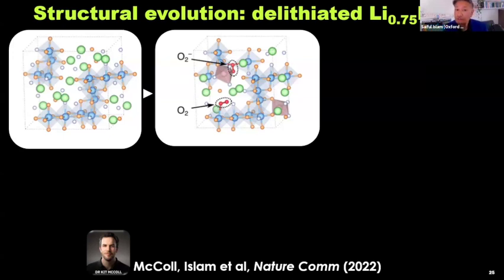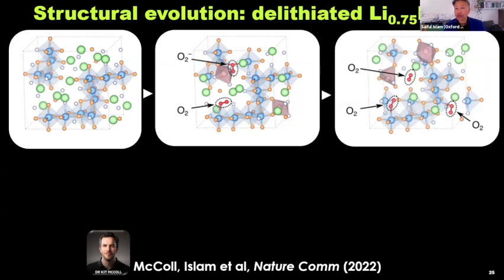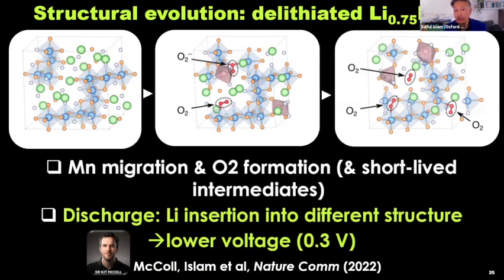And that's interesting, because these superoxide and peroxide species could be transient, because the thermodynamic product is again molecular O2 trapped in these nanovoids. So what we're seeing is manganese migration, O2 formation, and some short-lived intermediates. And on discharge, the lithium insertion is into a different structure, and that leads to a lower voltage or hysteresis.